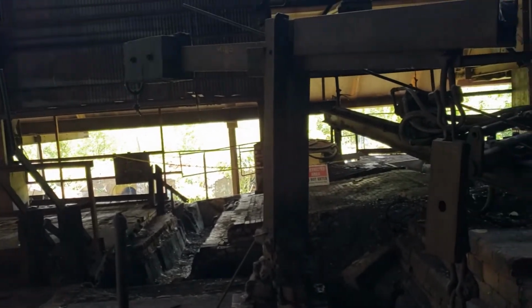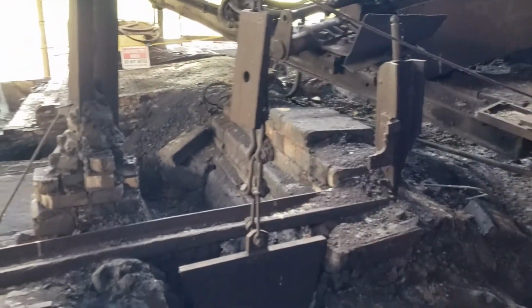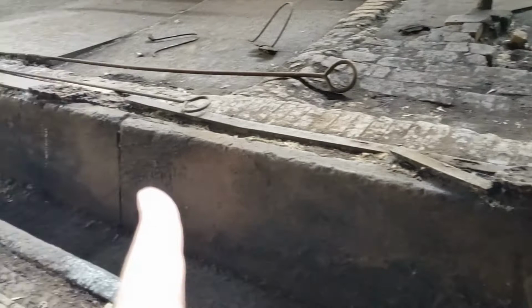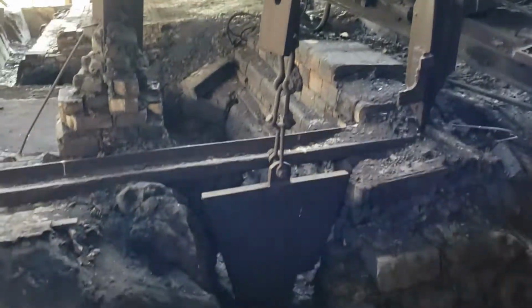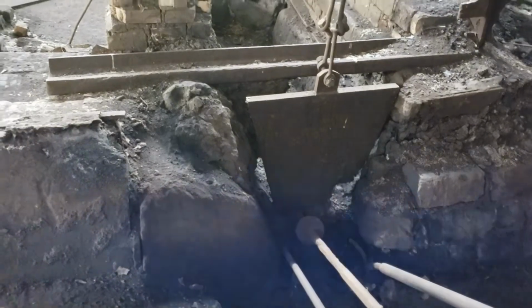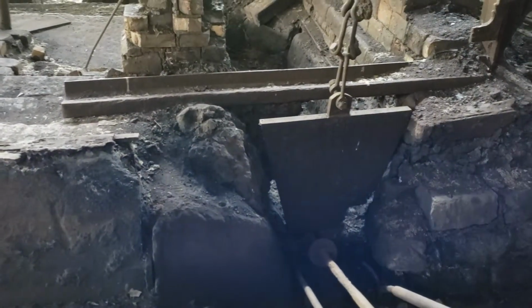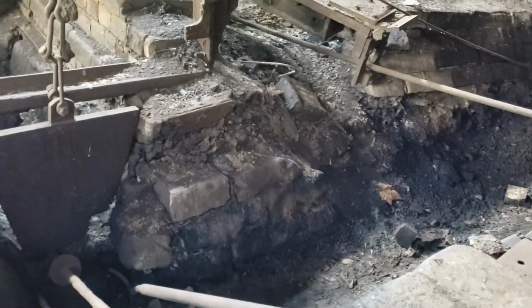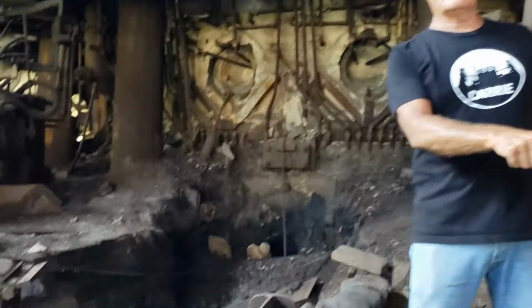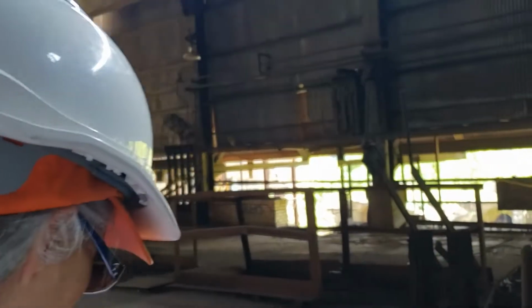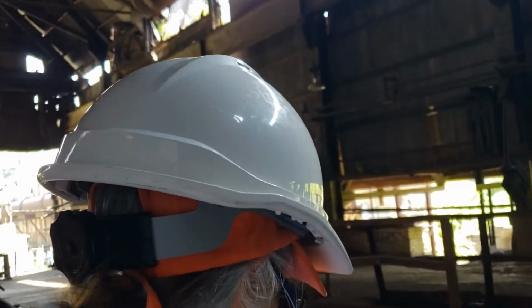And whenever you filled one, you'd create a dam system to get it to flow to the next one and the next one. The iron would flow under the slag through these runners and into ladles that are down underneath us. We'll see a ladle later when we see that. But the material flows through these runners into the ladle down below, which is called a torpedo ladle, a submarine ladle, or just a hot metal ladle. And you'll see those down beneath us. Then when that ladle got filled, you would then divert the iron to flow in the other direction and fill another one. So you'd get between 200 and 400 tons of iron out of each cast.